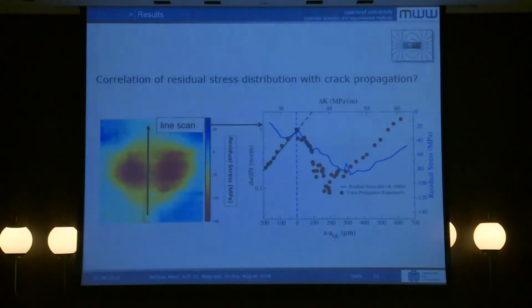So now you can also make a quantitative or more or less quantitative analysis of your stress field here in this direction, and then you will see that your compressive residual stresses you have here correspond very well with the crack propagation rate you find in your experiment when the crack is growing through this plastic zone and through this residual stress area in front of your crack tip.